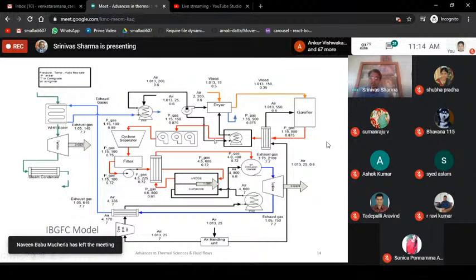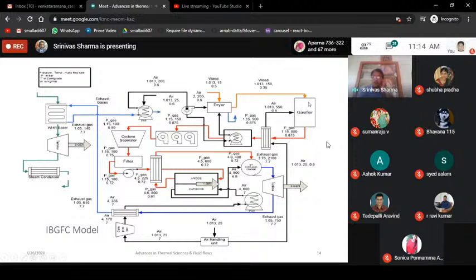There are various effects. So this particular wood is sent into the gasifier, and from the gasifier this wood is gasified. This is not a small thing, because this is only a small rectangle, but this particular process is very cumbersome. Wood has to be dried, then pyrolyzed, then you observe partial oxidation, then you have reduction, and then you get producer gas. And this producer gas is passed through a heat exchanger, wherein the air you are sending into the gasifier has to be reheated.